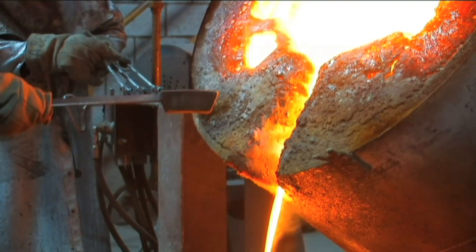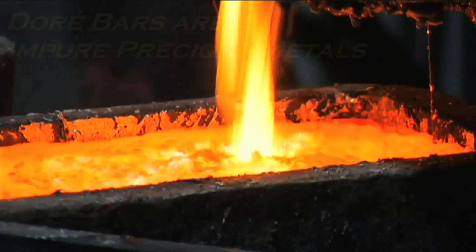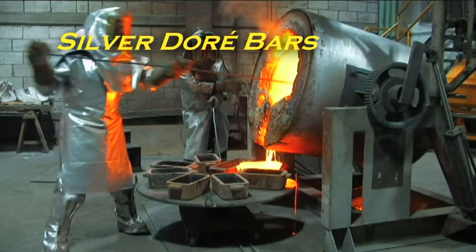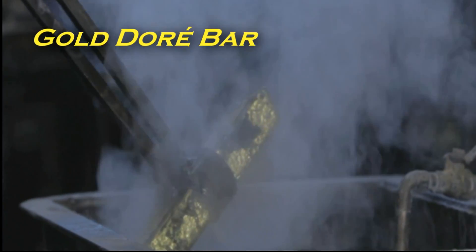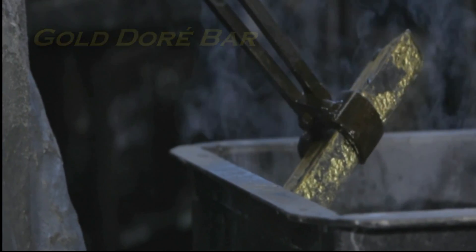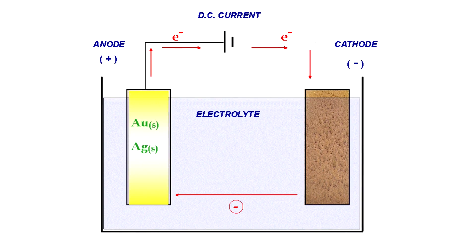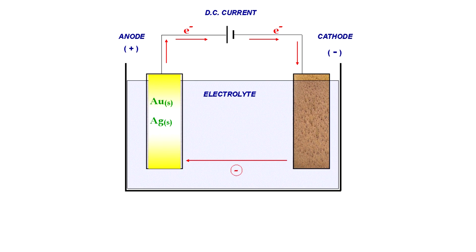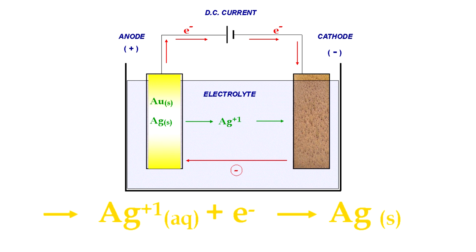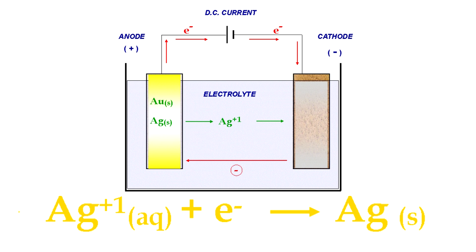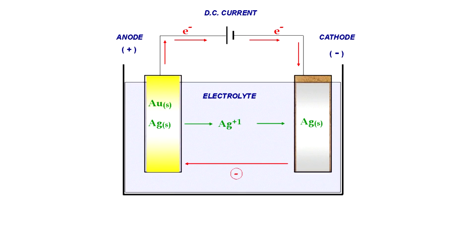An example of this is the process used to separate gold and silver from alloys. Doré bars produced at silver mines are semi-pure alloys of silver with small amounts of gold and other metals. These other metals precipitate out along with silver during the cementation process. The gold-silver alloy metal is used as an anode, and the electrolysis draws the silver into solution as the silver is stripped of electrons and transformed into silver ions. The silver ions then take back electrons as they plate onto the adjacent cathodes, resulting in pure silver depositing on the cathodes and a gold-rich material being left behind for further refining.